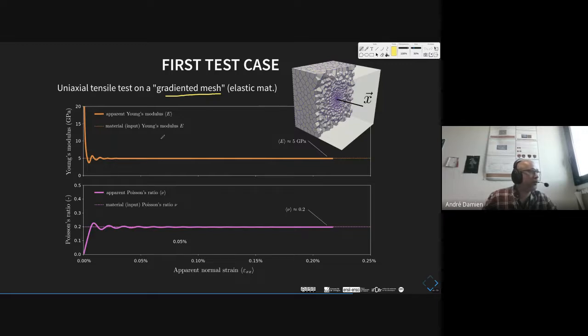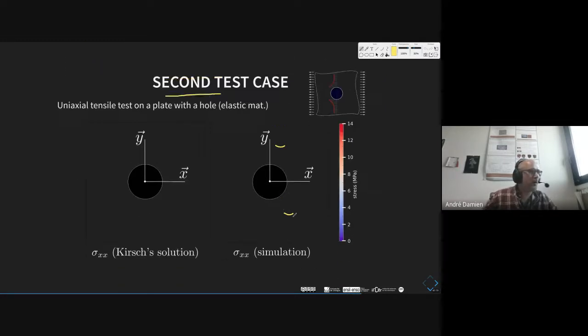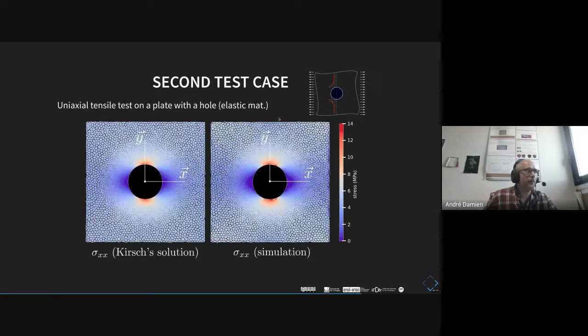And here, just to introduce, we put as input parameters a Young's modulus of 5 gigapascal and a Poisson's ratio of 0.2, and we get at the apparent scale more or less the same value. So it's a very good result. I'm quite happy with this result. So now the idea is to test something more complicated.